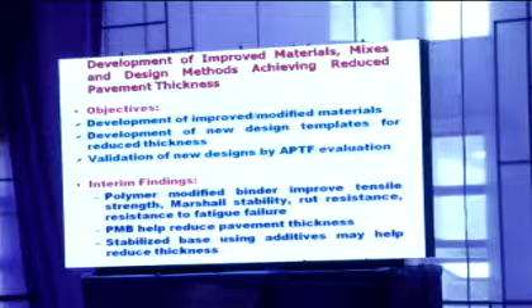The next project reported is development of improved materials, mixes and design methods achieving reduced pavement thickness. Interim findings are that if you use polymer modified binders, it will not only help improve tensile strength, Marshall stability, rut resistance and resistance to fatigue failure of the bituminous mixes, but it also helps in reducing the overall pavement thickness. Stabilized bases are another option which can be used to reduce the overall pavement thickness.